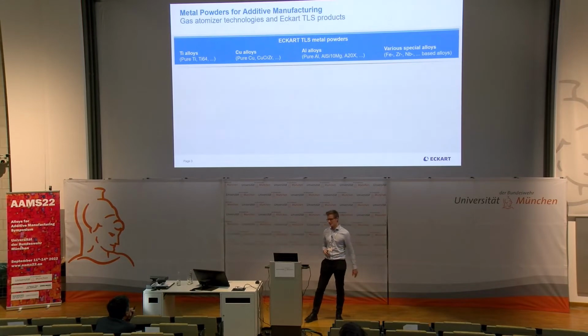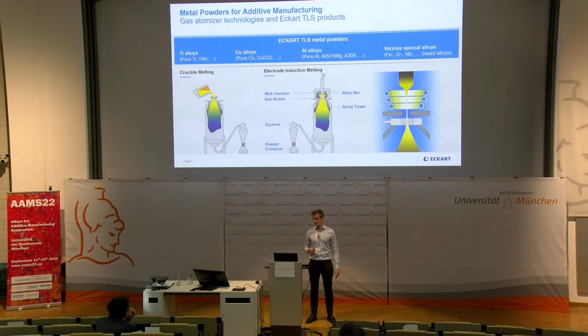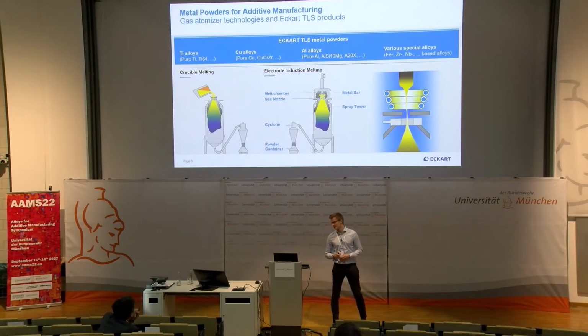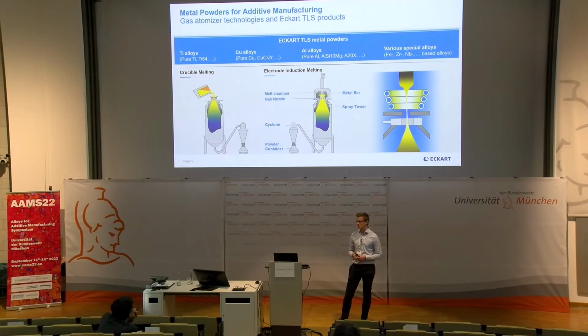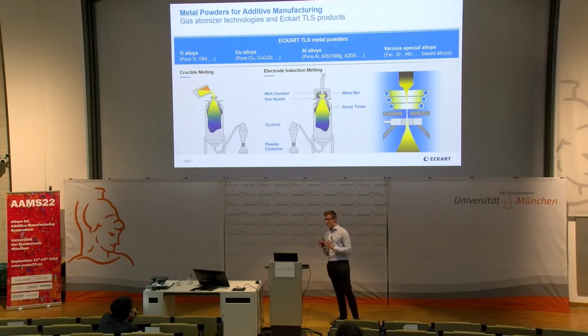And these are the types of alloys that we produce. Our specialty is titanium, copper, aluminium-based alloys, even though we can atomize pretty much anything, as long as it's not radioactive or highly toxic, and as long as it's conductive, which is very much related to the atomization techniques that we employ, because next to standard crucible-based atomization, we also use a crucible-free process, which is electrode induction melting inert gas atomization, which is good if you want to atomize high melting materials or highly reactive materials such as titanium. And one of the alloys that we atomize using electrode induction melting is A20X, okay?